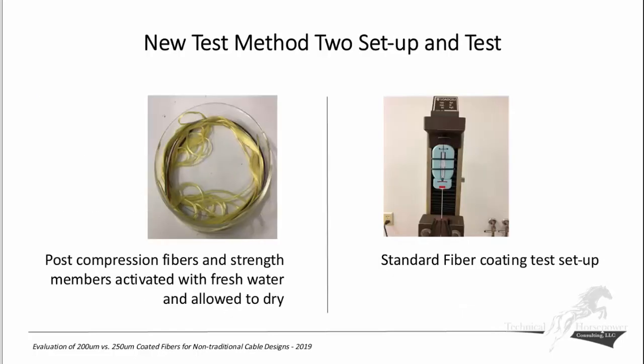And what we did in that is we took the post-compression fibers and strength members that were imbued with various water-swellable agents, put them in a Petri dish, activated it with fresh water, approximately 2-3 hours of time with the water, dumped out the excess water, and then allowed the powder to dry again. 24 hours after it was dry, we took it to the standard fiber coating test setup you see on the left, which was in the instrument. We used a standard tool and pulled 30 centimeters. And basically, the nominal values on this, FOTP 31, is between 1 and 9 newtons for a 30 centimeter section of material.